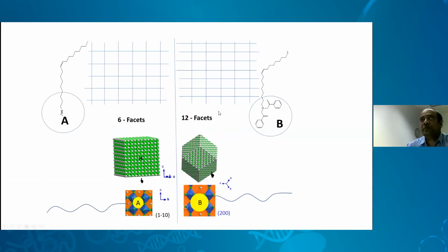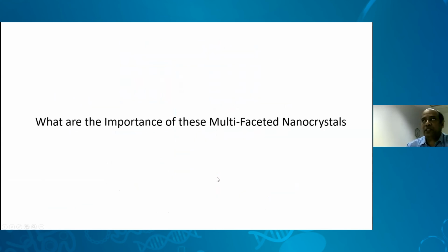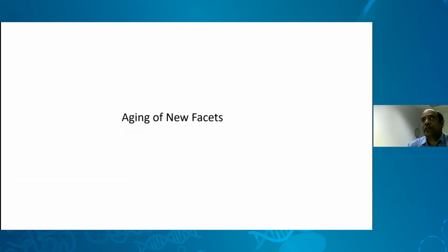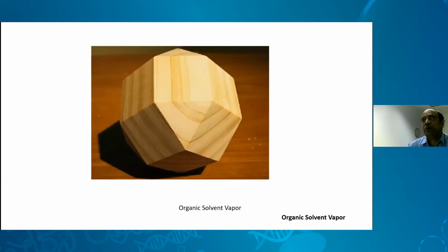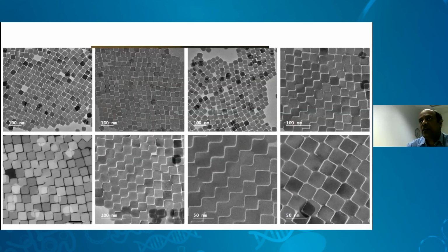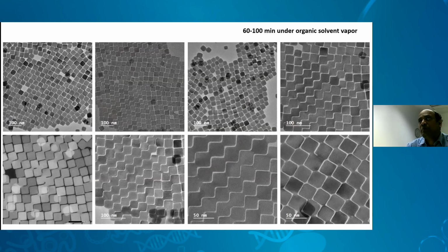So we conclude this way: 6-faceted, 12-faceted, what we have found, and they can give different types of nanostructures. What is the importance of these multifaceted nanocrystals? Certainly we found that for catalysis, these are better than the cubes because they have new facets. And one more important feature: once we keep those structures aging, meaning kept some time in the organic vapor, we found that this particular set of nanostructures are connected. They are connected one to another through the kernels, even for hundreds of nanometers. You could see that it can go even to the 1 micron range, beyond the micron range.